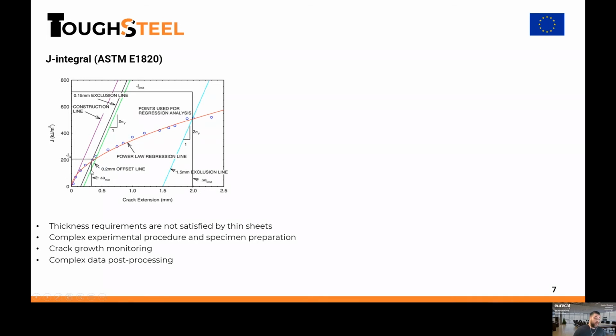These J1C values, or the single initiation toughness value, are known to be very conservative when the material has a significant contribution from stable crack extension. So in this case, the full J-resistance curve should be provided.